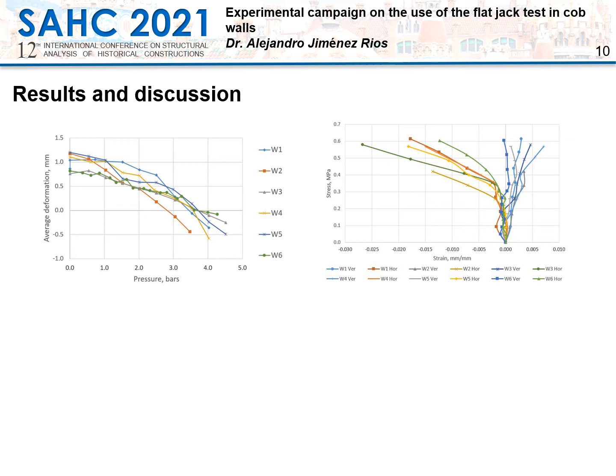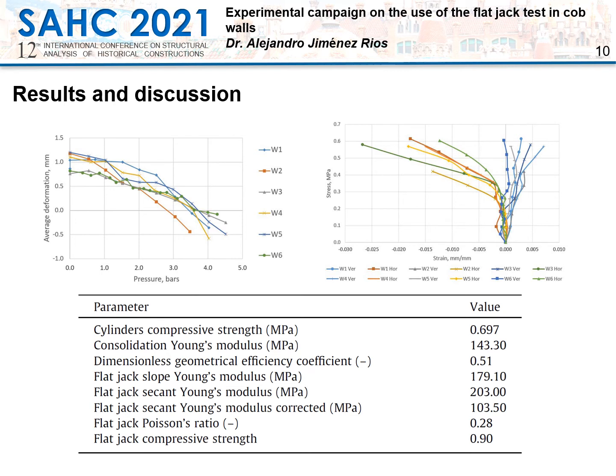The values obtained for the mechanical parameters of cob wallets are the ones shown in this table. Here we can also see the reference value obtained from the compressive test of the cob cylinders and Young's modulus obtained from the consolidation process of the wallets. The Young's modulus of the material, estimated by taking into account the slope of this last elastic range on the stress-strain curves, was in good agreement with the value obtained from the slope of the consolidation process stress-strain curves. As highlighted by the t-test, no statistically significant difference was observed between the mean value of both groups.